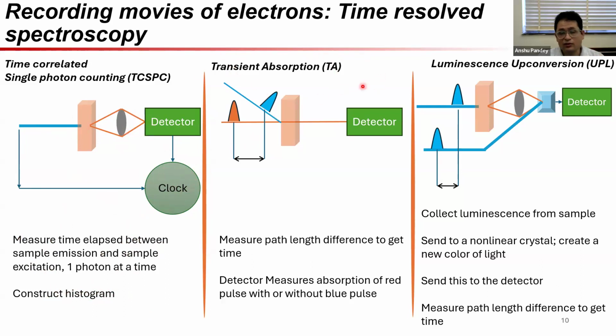We have a different technique as well, which is transient absorption. This is slightly different because it uses path length differences between two pulses to actually measure time, multiplying by the speed of light and all. The first pulse is a very strong pulse. This is incident upon the sample, and this causes the sample to start having an electron hole pair inside it. The second pulse, which is this orange pulse, then arrives, and a detector checks how much is the change in absorption of this pulse with and without this particular blue pulse being present. So what this essentially does is the same business as TCSPC is doing in emission; this thing is doing in absorption. Again, if there are electrons dwelling in any state, we can find out that indeed those electrons are still there.